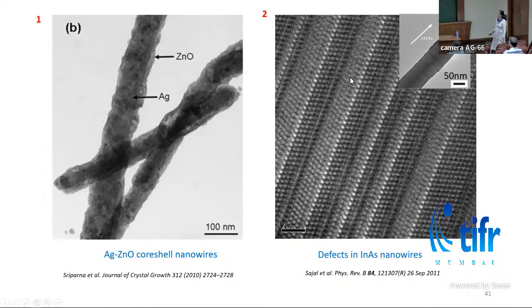So this sample is a very good example of defect engineering, because here, after measuring the thermal conductivity of these nanowires, we found that the thermal conductivity of these defective nanowires was 1,000 times less than that of the bulk indium arsenide.